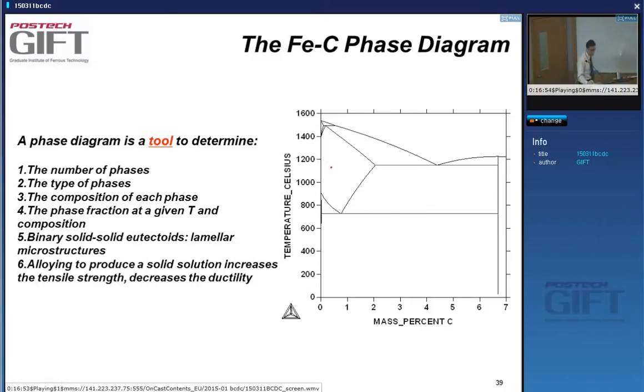You know that this is the austenite stability field, yes? And in this field, we have ferrite plus what I usually write down as theta. Theta is just cementite, yes? So what you see is normally here at about 912 degrees C, the austenite transforms to ferrite as if we have pure iron. So pure iron is along this line here on this diagram, yes.